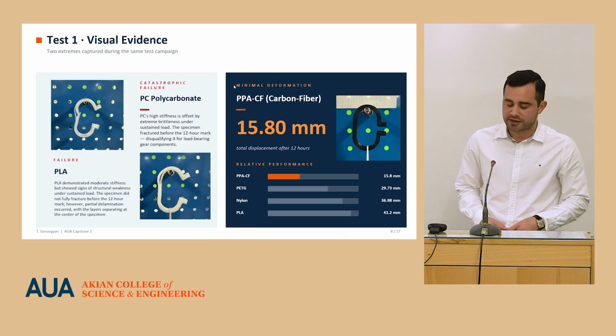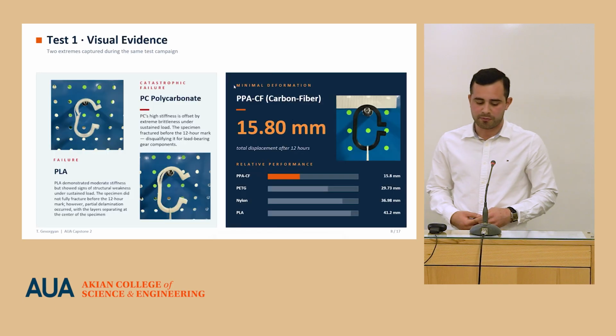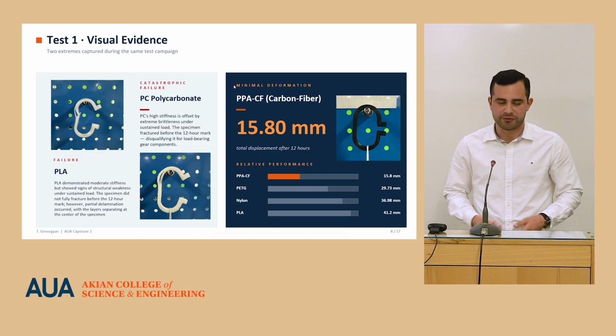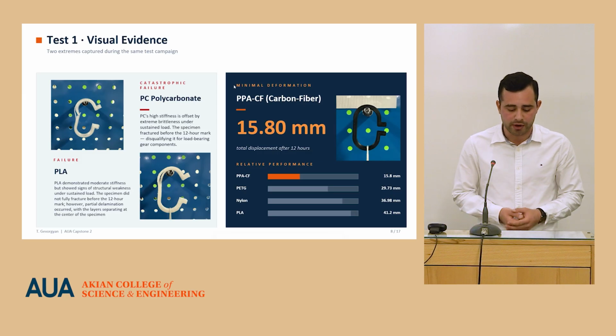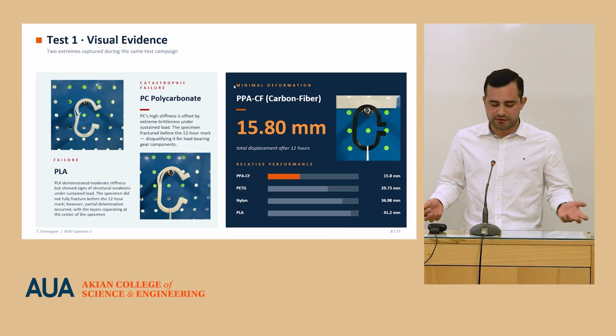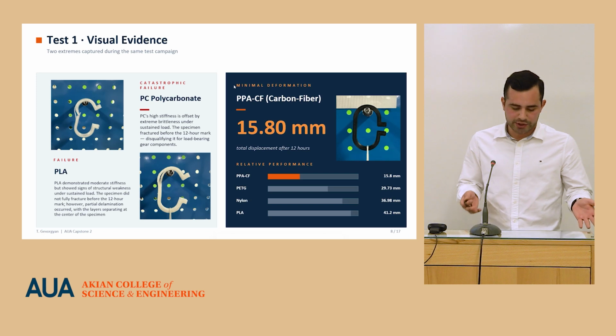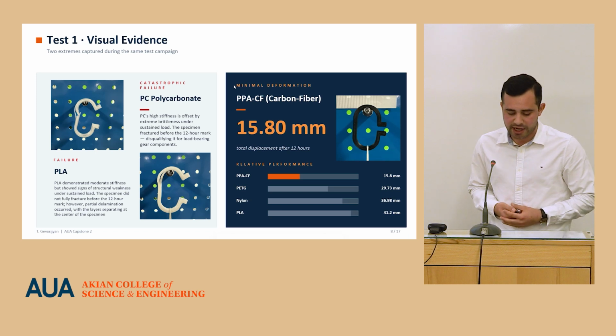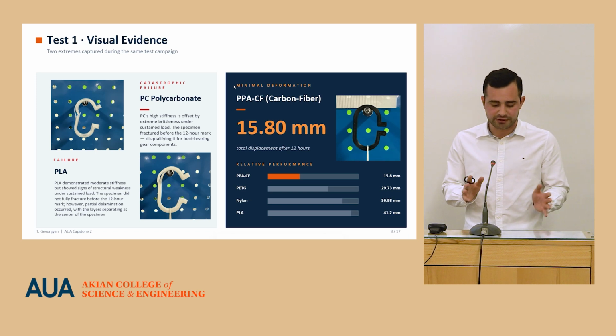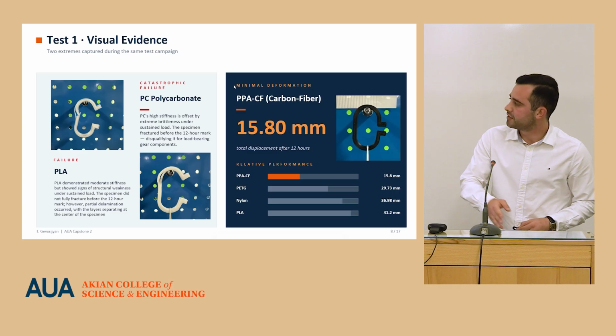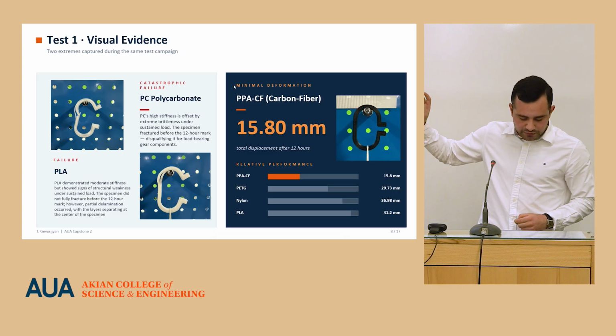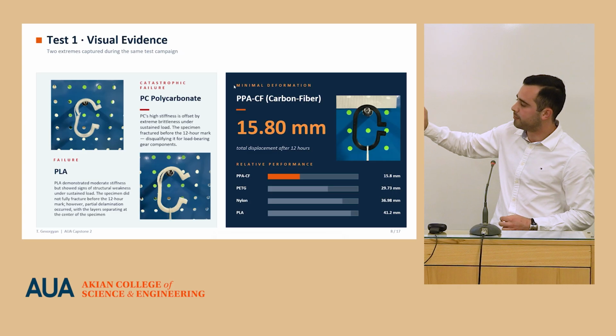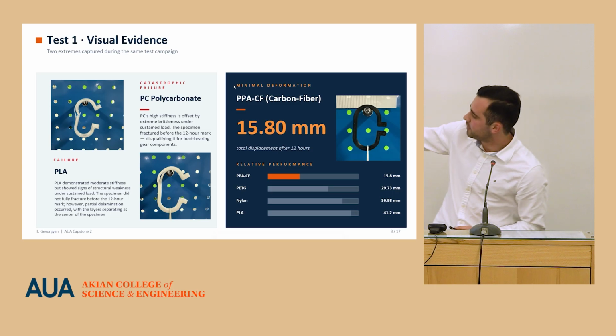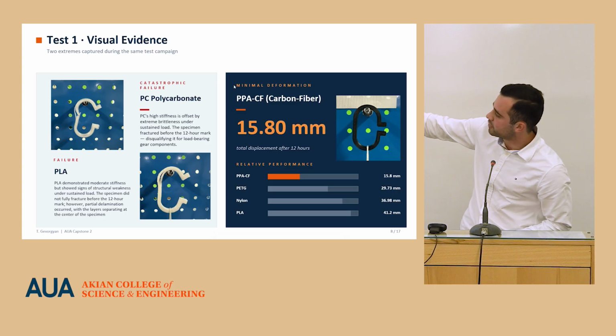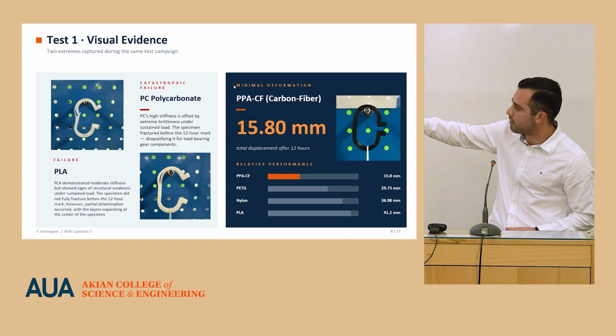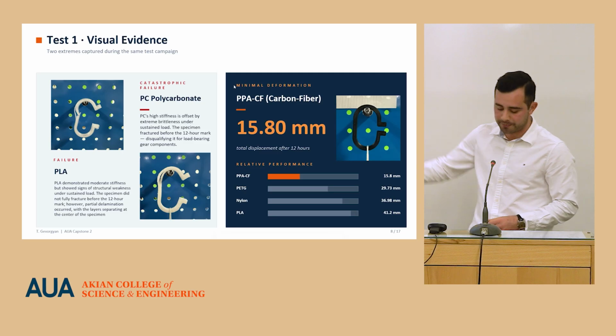And here you can see some visuals from these tests. The polycarbonate broke before even hitting the 12-hour mark, which can be considered a failure. And PLA half failed this test because, as you can see, the layers were separated from each other, and you can see how small the deflection in the carbon fiber is after 12 hours of constant load.